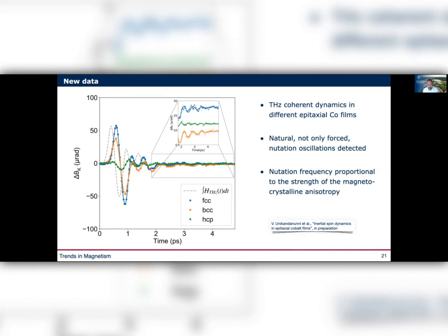We'll soon put this paper out. It seems that the damping at terahertz frequency is much larger, so you cannot use the Gilbert FMR damping to explain the dynamics here. If you assume the Gilbert damping is larger at these frequencies, probably because the scattering mechanisms at different energy scales are different, then you can fit this. And this would also explain the disagreement in the paper.